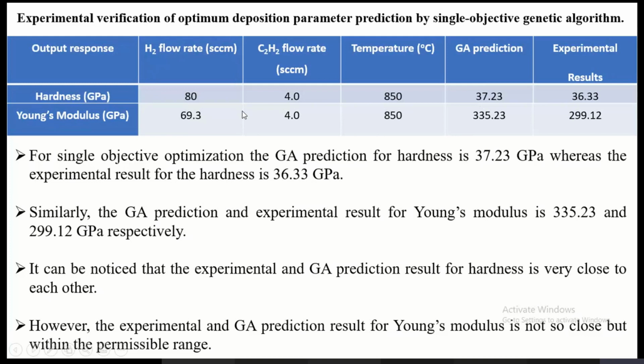From the model which we had made, we got a hardness of 37.23 gigapascal and a Young's modulus of 335.23 gigapascal. Then we conducted the same experiment with that particular setup and observed an experimental hardness of 36.33 and a Young's modulus of 299.12. In the case of Young's modulus, some deviation was there between the GA prediction and the experimental result. However, in the case of hardness, we observed a very close value, which signifies that for hardness, this is predicting an accurate result.